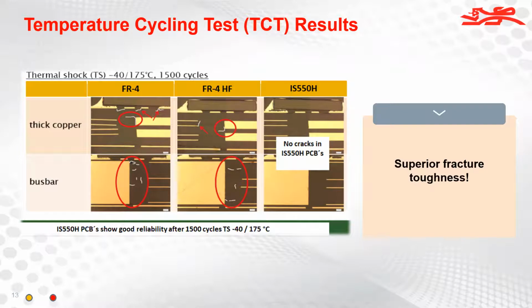And typically what we see when we do this type of thermal shock on a traditional FR4 or traditional FR4 type halogen-free material is we see cracks. We see a lot of cracks. So you can see those in the red circles there. When you take the IS550H and subject it to this same type of testing, you don't see those cracks. So you're able to go through these harsh, punishing thermal cycles for many, many cycles. In this particular case, it's 1500, and you don't see the cracks. Again, that's because of its superior fracture toughness.